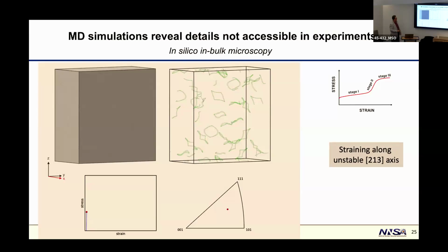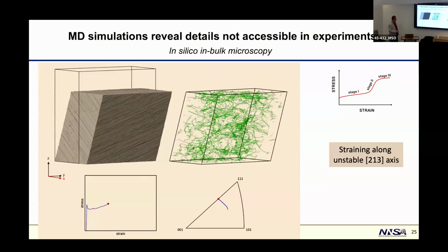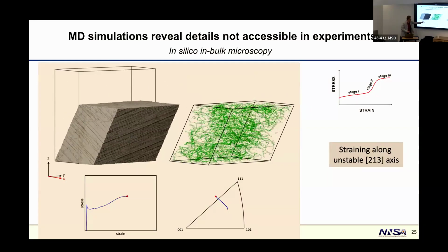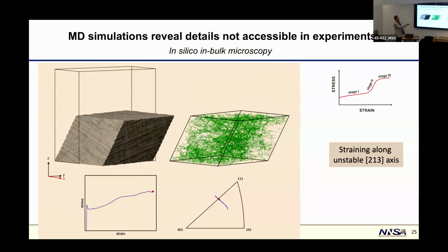Next. This one starts here. This is the axis orientation. I don't need magnification anymore to show what happens to the specimen axis. It actually rotates visibly by quite many degrees. Look at this curve. So the crystal rotates. There's 3-stage hardening. It's pretty much what was expected.